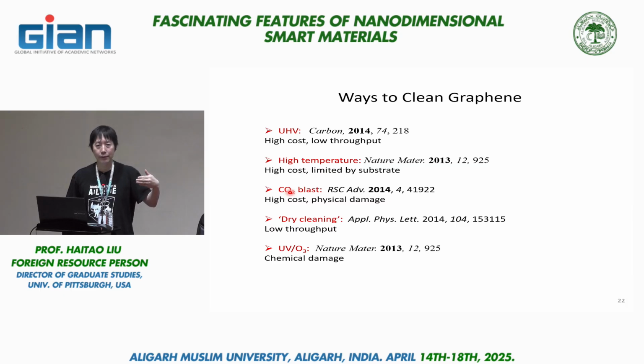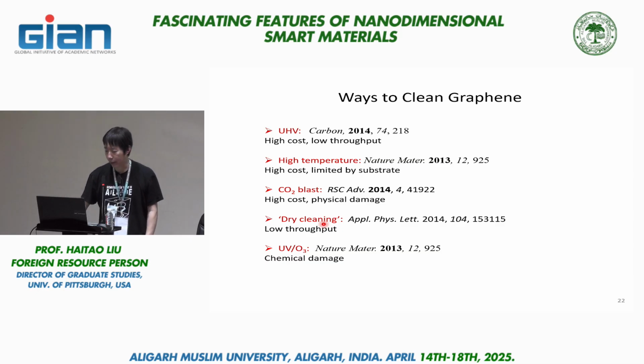So in a sense, you can wash the surface, but you are not leaving any additional contamination from the solvent. Okay, so this works quite beautifully, but also you're blasting the surface with solid particles. You could damage the surface, and also this is a pretty expensive process. And then some people try so-called dry cleaning. Basically it means they add some other sorbent to capture the hydrocarbon. That seems to work in some limited cases as well.